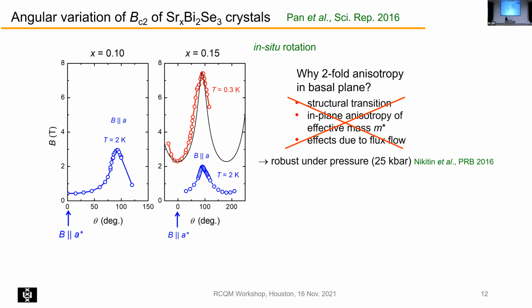Moreover, we did the same experiment under high pressure and up to pressures of 25 kilobar, and the effect remains there. So it seems to be really robust. So we really have broken rotational symmetry. And so we have to explain that. So we have to go to the theory.